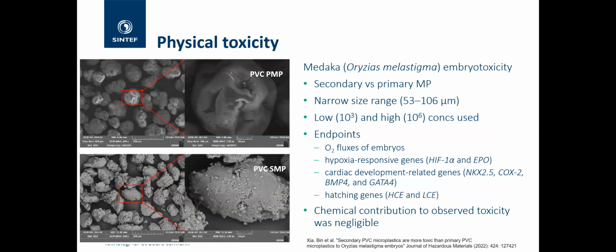So I'll just give an example of this, of a study that we just published this year. It's a collaboration that we had with a research group in China. And here we were trying to look at the differences of more spherical particles. They weren't as spherical as we'd have really liked, versus really regular shaped particles. So we wanted to see if there was a difference between these primary and secondary microplastic, and we used PVC particles. We purchased the spherical ones, and we created the irregular shaped secondary microplastic using milling.